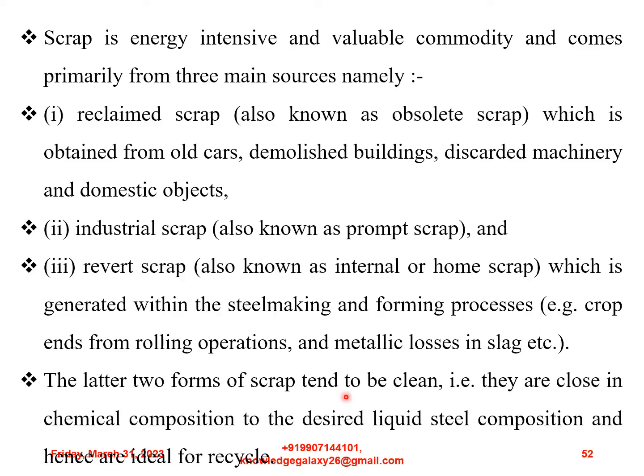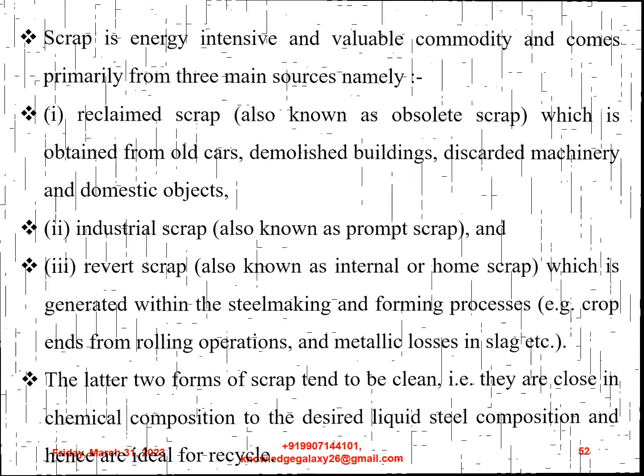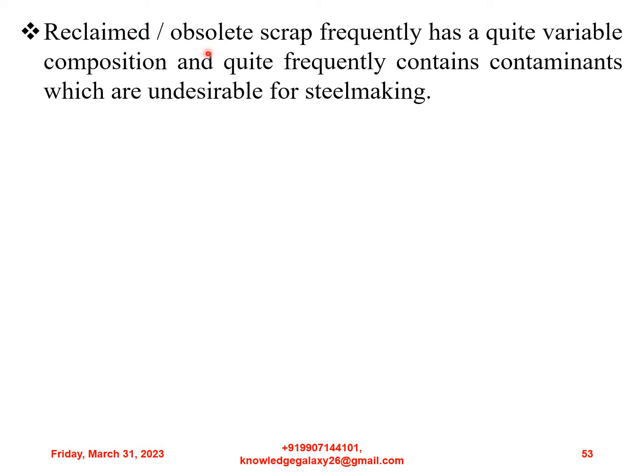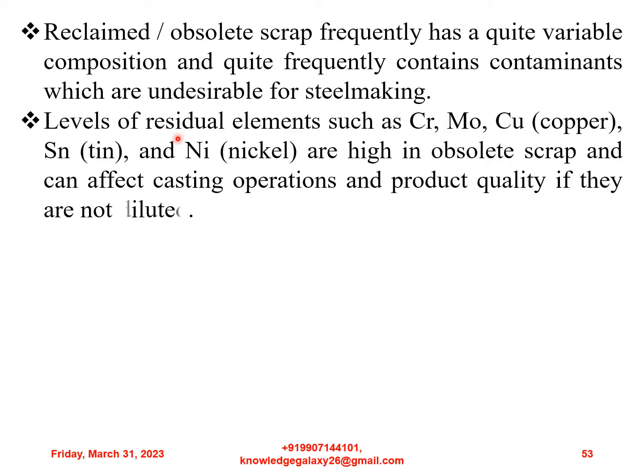The latter two forms of scrap tend to be clean, that is, they are close in chemical composition to the desired liquid steel composition and hence are ideal for recycling. Reclaimed or obsolete scrap frequently has a quite variable composition and often contains contaminants which are undesirable for steelmaking. Levels of residual elements such as chromium, molybdenum, copper, stannum, and nickel are high in obsolete scrap and can affect casting operations and product quality if they are not diluted.